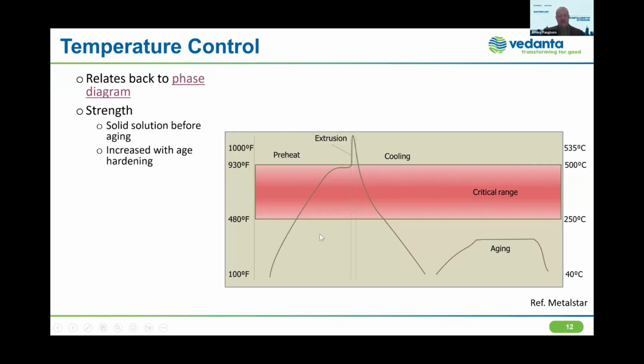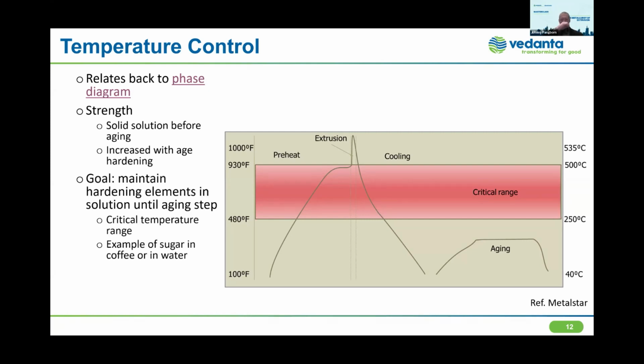So we have some strengthening from the magnesium and silicon in solid solution, but in aging, we're increasing that by controlling and having these really fine particles that we want. So in extrusion, I kind of mentioned it, but specifically the goal in extrusion is to keep those hardening elements, magnesium and silicon, in solution so that we can age later.